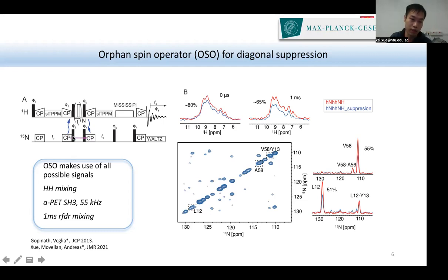We can make use of these signals by flipping back to Z, and naturally T1 is long, so this signal is preserved. And since in this region N-spin diffusion is very inefficient at faster spinning, this signal here only contributes to the autocorrelated peaks. And if we make a negative sign, and we sum up for this transfer pathway here, we can subtract peak intensities in the diagonals. We also demonstrated this scheme using SH3.